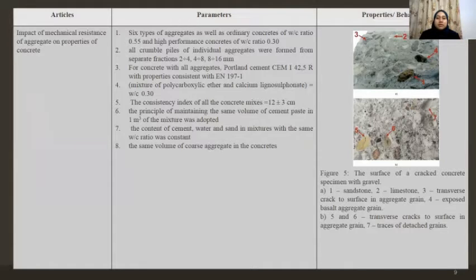The parameters used in this article are, first, six types of aggregates as well as ordinary concretes of 0.55 water to cement ratio and high performance concretes of 0.3 ratio. All individual aggregates were formed from separate fractions, which are 2 to 4, 4 to 8, and 8 to 16 millimeters.